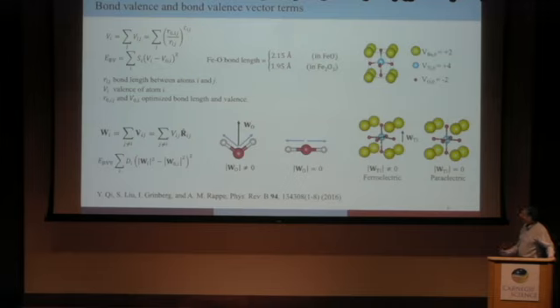Okay. And then this bond valence vector, you can see an example here that if we calculated bond valence for water, it might have two perfectly good OH bonds and be happy, but it wouldn't know that water actually wants to have a bend structure unless you reward having the sum of the two vectors be non-zero, and so you make a minimum around some value that would allow water to know that it should have a polar and low symmetry shape. And so that's been quite successful for us. Several students have contributed strongly to the methodology of bond valence, including both Yubo and Shi. So you will see some of the methodology work implemented here.